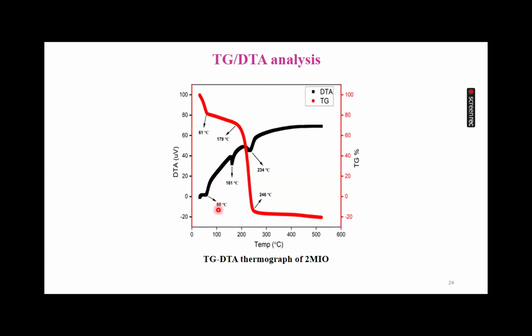From DTA, the material's weight losses start at 60 degrees Celsius, while the decomposition temperature is 161 degrees Celsius, which indicates the process of gradual weight losses for the sample. Furthermore, the dissociation temperature of the material is 234 degrees Celsius, at which there is a heavy weight loss of the sample, because of a simultaneous melting and dissociation point being reached. Also, the TG shows that the minor weight losses start at the temperature range 61 degrees Celsius to 179 degrees Celsius, and the major weight losses occur to 246 degrees Celsius.